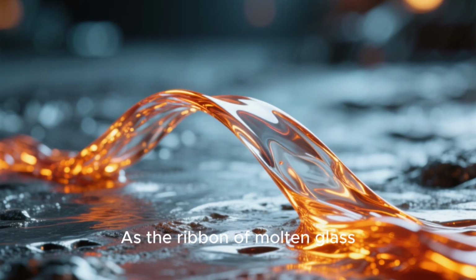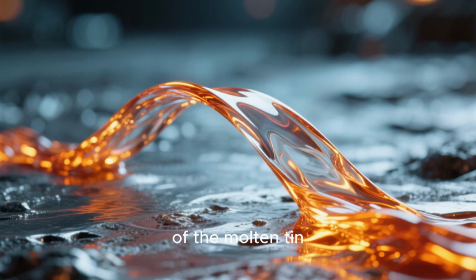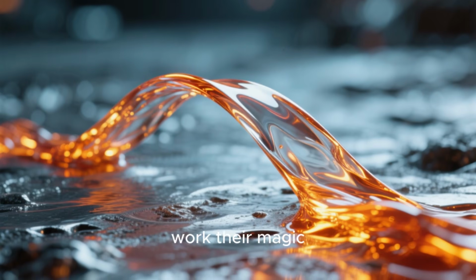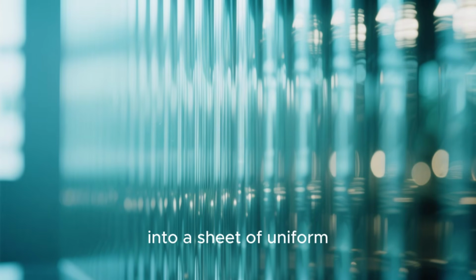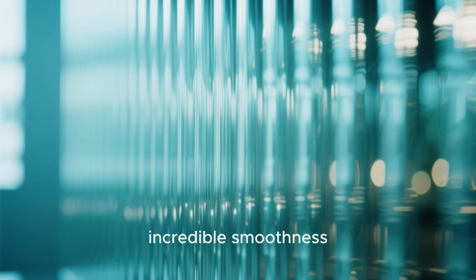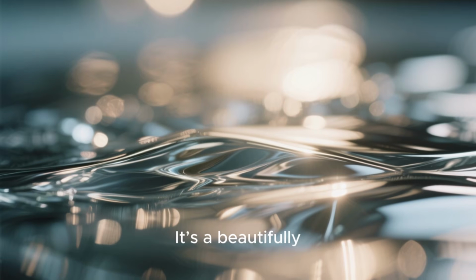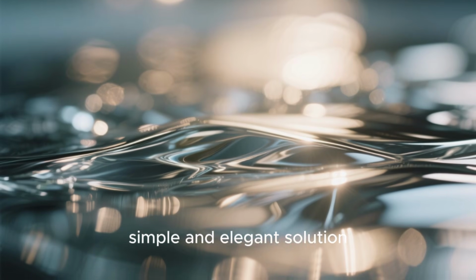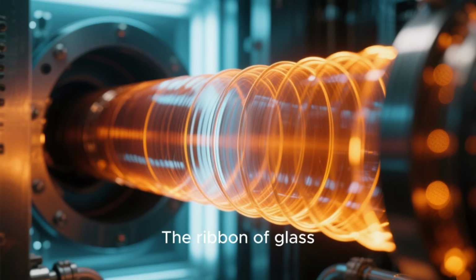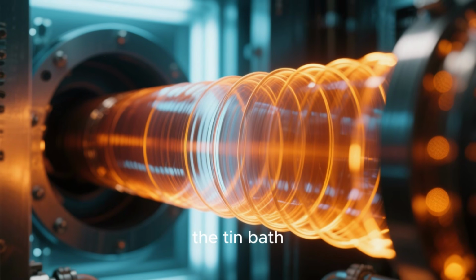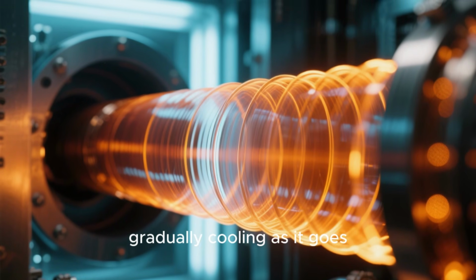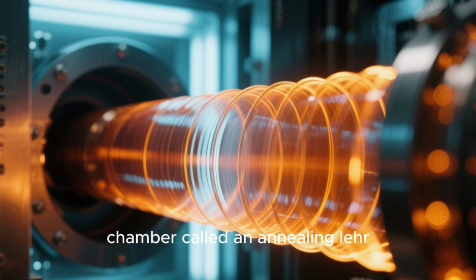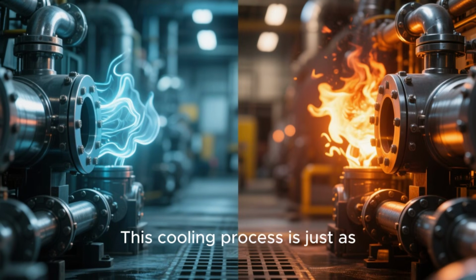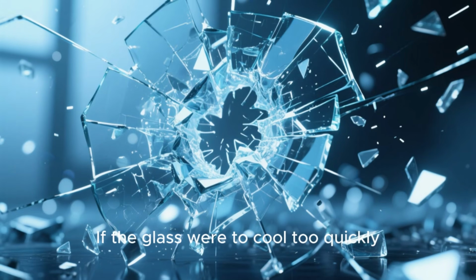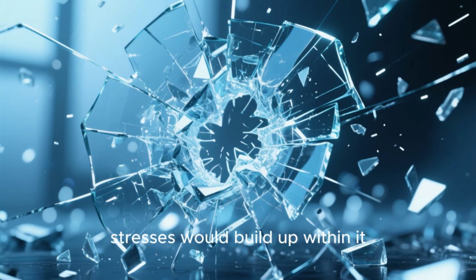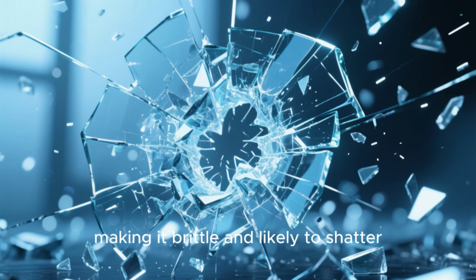As the ribbon of molten glass spreads across the perfectly flat surface of the molten tin, gravity and surface tension work their magic. They pull the glass into a sheet of uniform thickness and incredible smoothness. There's no need for grinding or polishing. It's a beautifully simple and elegant solution to create flawless sheets of glass. The ribbon of glass then slowly moves along the tin bath, gradually cooling as it goes. It enters a special cooling chamber called an annealing lehr. This cooling process is just as critical as the heating. If the glass were to cool too quickly, stresses would build up within it, making it brittle and likely to shatter.